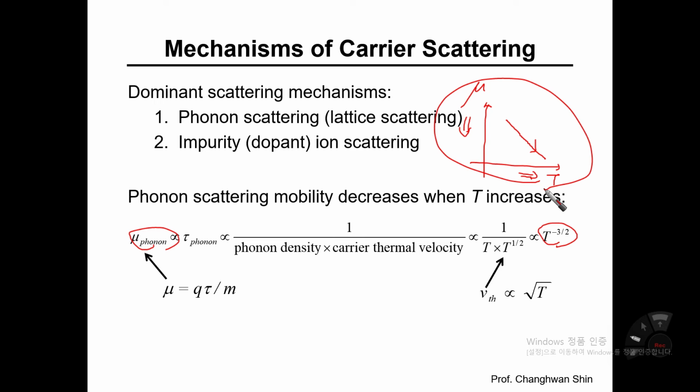So it would cause significant phonon scattering. As temperature increases, the electrons and holes, those two carriers, find it very hard to move forward. In that sense, the mobility of each carrier is hurt and degraded when the temperature increases. All of these things can happen by phonon scattering.